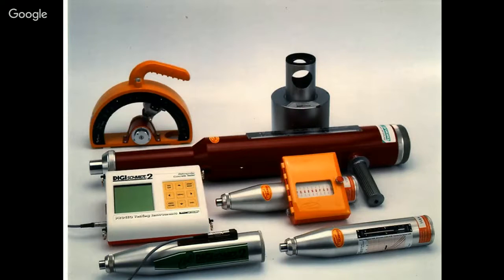Regarding accuracy, 2 days back we were testing a bridge, and the engineers had tested cubes for 7 days, and those 7-day strengths failed. So they were having the test for 28 days and all that. On the 22nd day we carried out the test using the rebound hammer, and found the value was giving strength up to M60, a high strength concrete, and we told them this is the strength. Another private person tested that concrete using his own instrument, which was not properly calibrated, and said it is poor quality concrete and the strength had not developed.